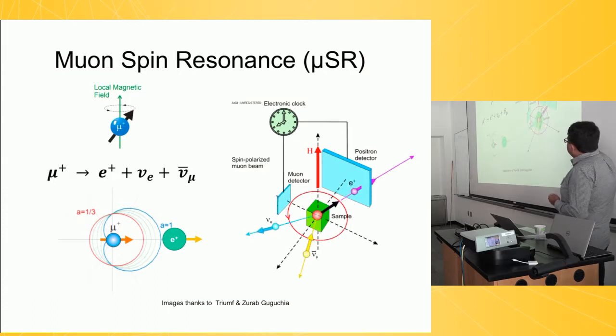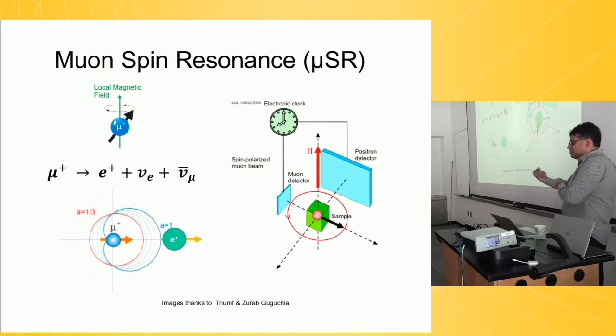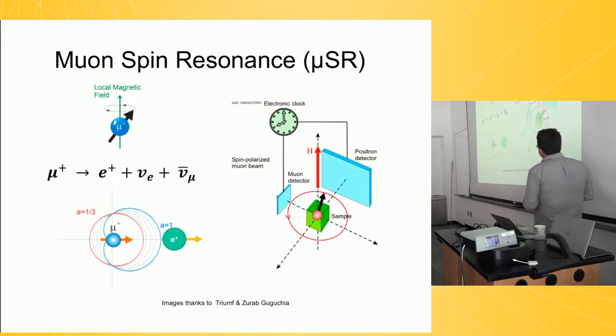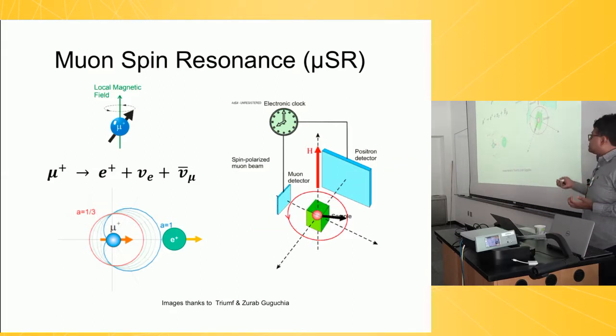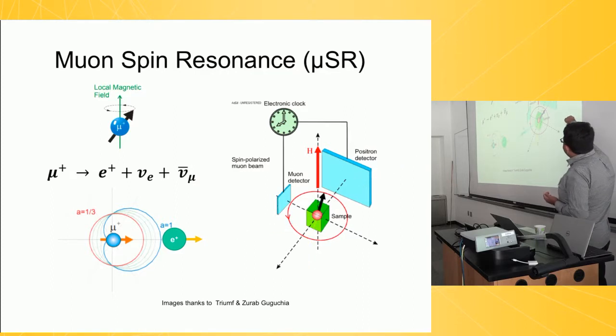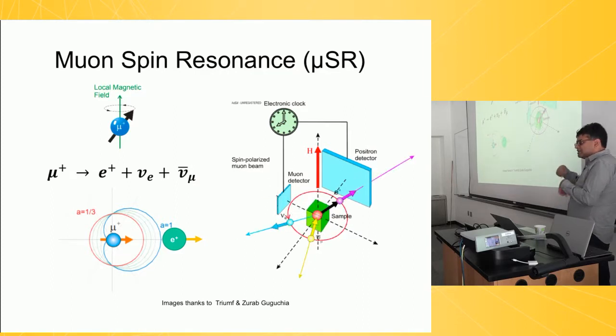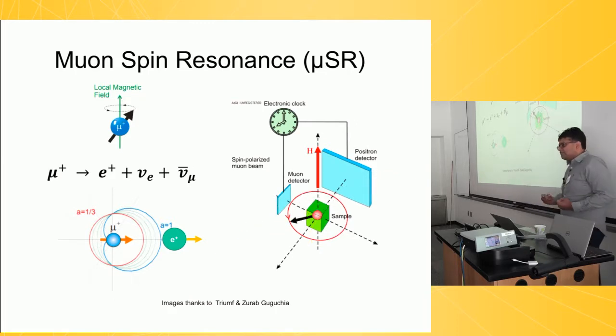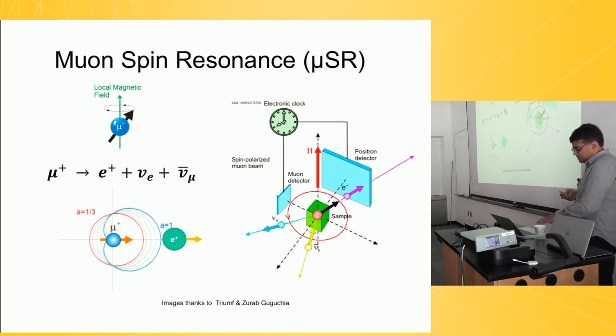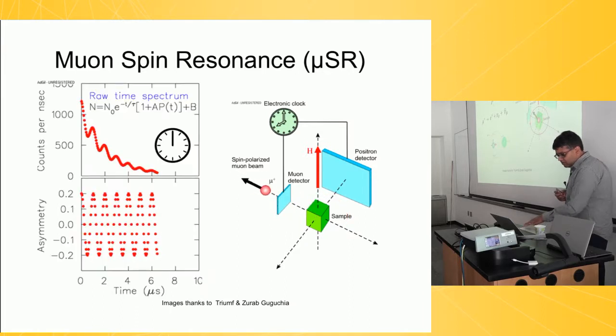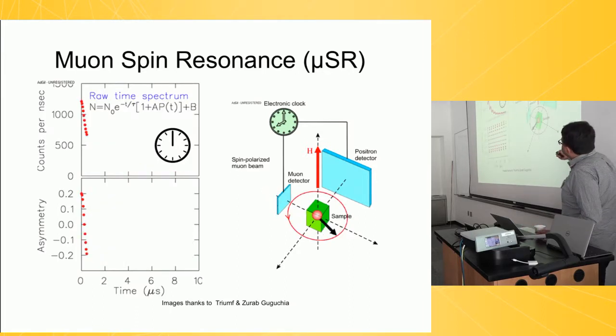After some time, the muons will decay, and they're going to decay and produce positrons. You have positron counters on all sides of this crystal. You measure how many positrons you get, for example, in this direction, compare it to how many you get in this direction, and from that asymmetry, you can say something about what the internal magnetic field is in my crystal.